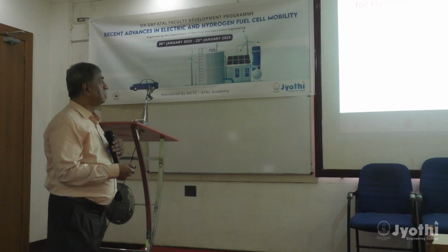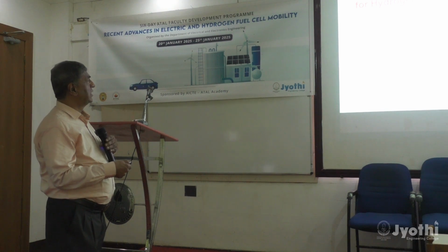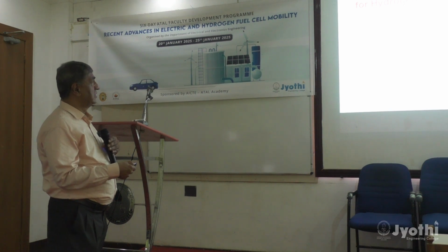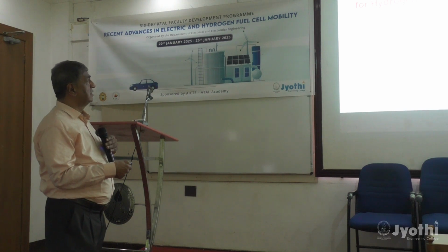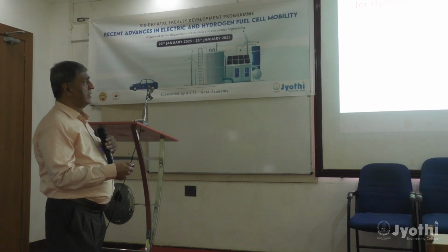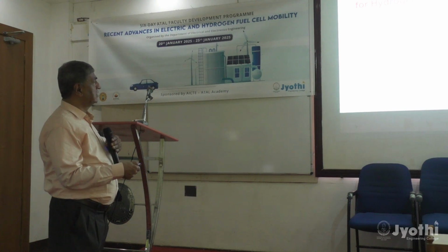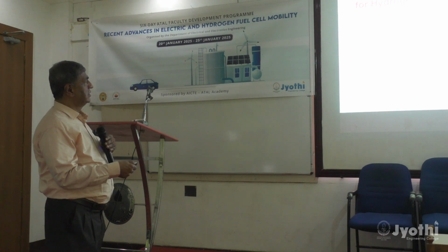And I was mentioning the two-step thermochemical water splitting. If you have a metal oxide, when it is reduced, it produces some oxygen vacancies. Depending on what the metal oxide is, the temperatures can be 1200, in fact, we found even from 900 onwards good activity. So oxygen vacancies are produced, and then this reduced oxide is a very active component. On that, if you pass steam, it will pull the oxygen from the steam, go back to the original state, and hydrogen gets produced.